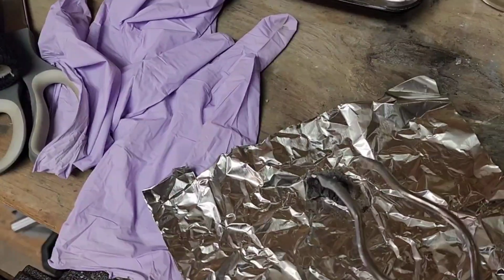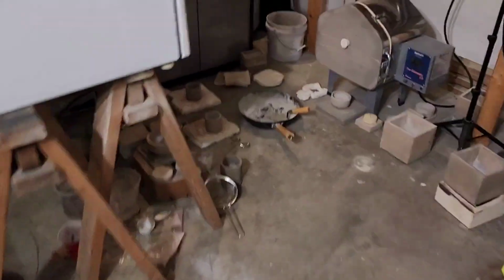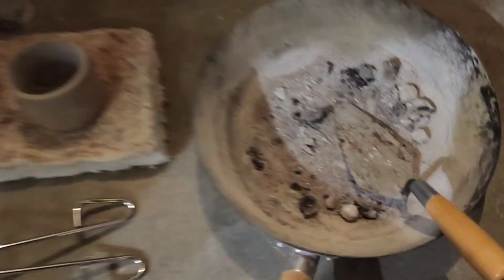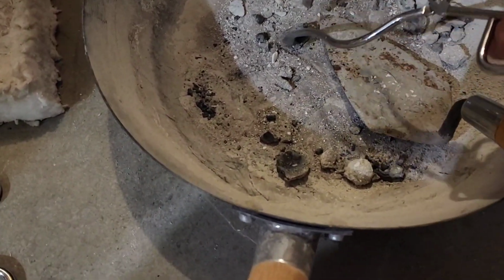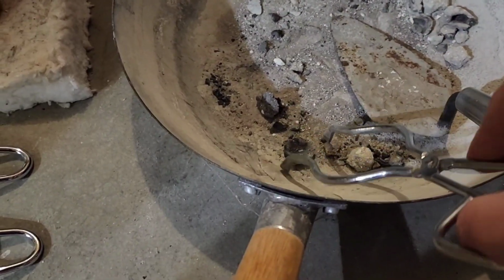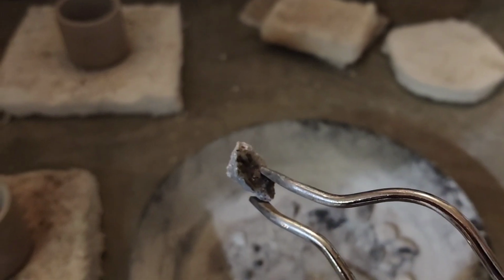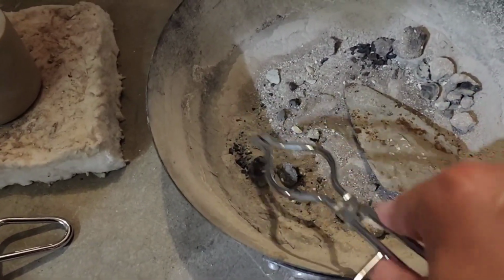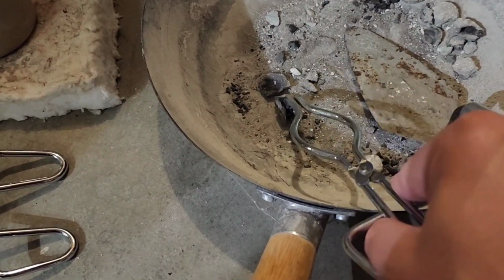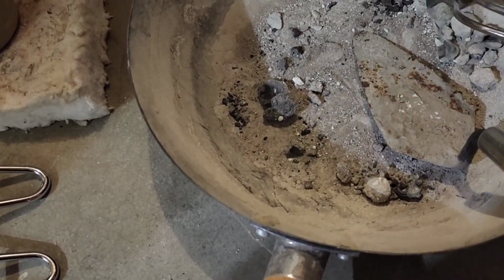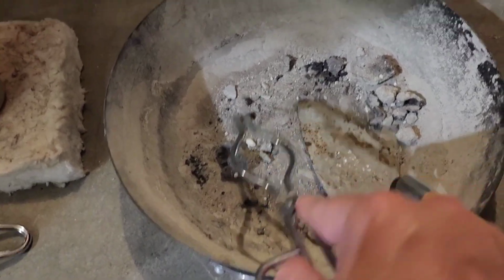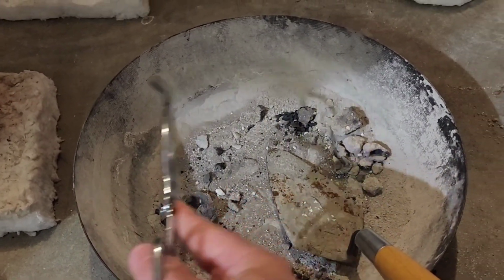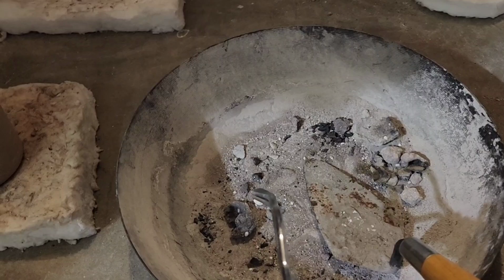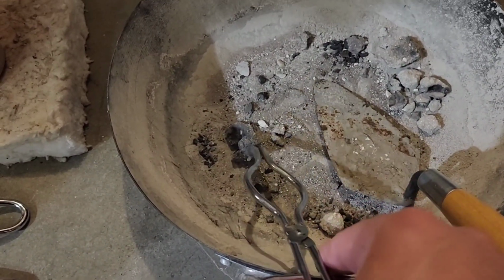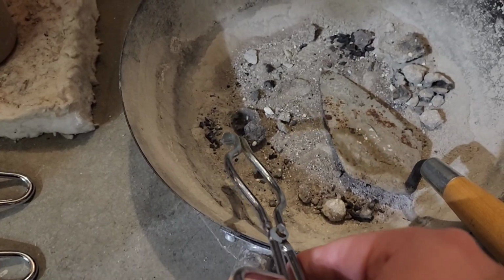I know it's in pieces at the moment, but when we take a look at the pile over here, I really had to smack these things open. A lot of people probably don't realize that it forms a shell around the parts, which is very challenging to get off. But what I did notice is that the shell on this side over here, the pre-sinter, and this side over here, the singular microwave arc sinter, this shell was very compact. It was very challenging to get open.